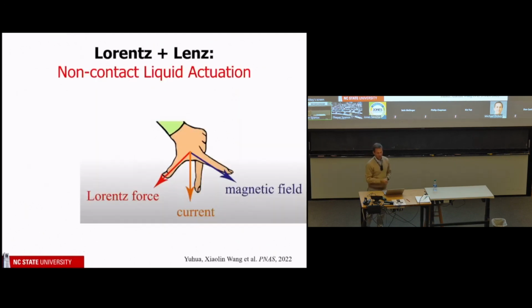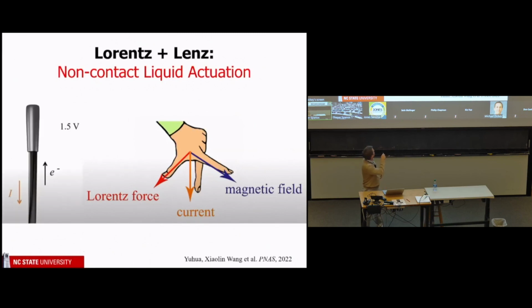And one of the cool things is, do you remember this from freshman physics? So in our wire, we've got current going through our wire. If we put a magnet behind it, we can get a Lorentz force. And the Lorentz force on a liquid, there's no resistance to it, so it should move. So if you imagine, here's our magnet, which you can't see because it's behind the screen, so I'll make that go away. But here comes the drop, and the Lorentz force whips it around outwards, and then it experiences Lenz's law at the perimeter of the magnet, and that slows it down because the magnetic field diverges at the edge.